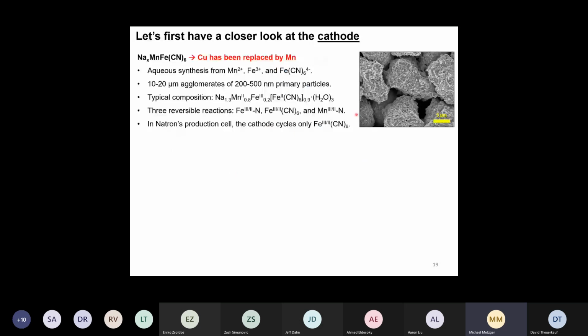Okay, so this is first a slide that deals with the cathode. On the right side, you see an SEM image of this cathode. You have these large secondary agglomerates made up of really small primary particles. And what they use as the cathode now in this Gen 2 is a sodium manganese hexacyanoferrate material. So they swapped out the copper, which was here initially, for manganese. And we can try to understand why they did this. But first of all, these materials are made in an aqueous synthesis.